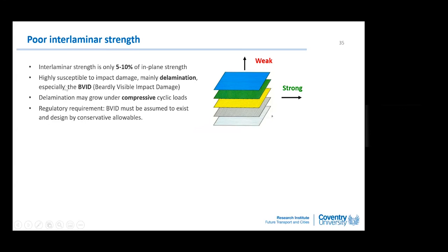I just want to say composites have very poor interlaminar strength. That is about 10%, 5% of the in-plane strength. So horizontally, they are very strong. It's impossible to fail, but vertically easy to peel, like you peel a banana skin, the strength is very low. So they're highly susceptible to impact damage.